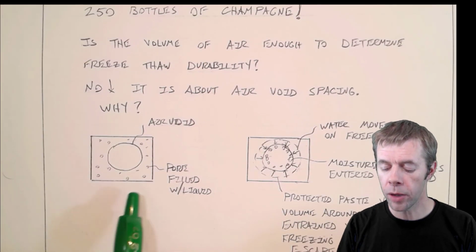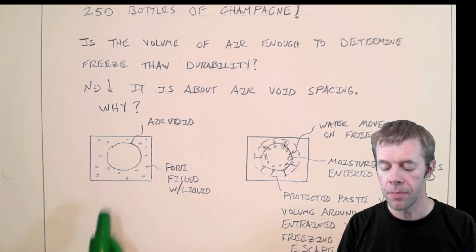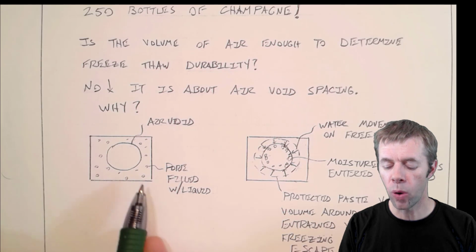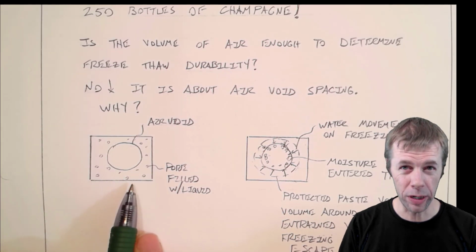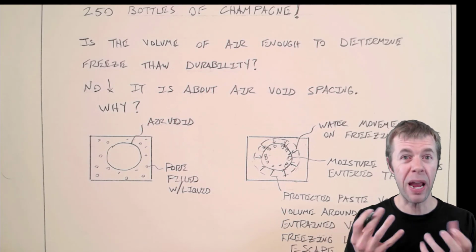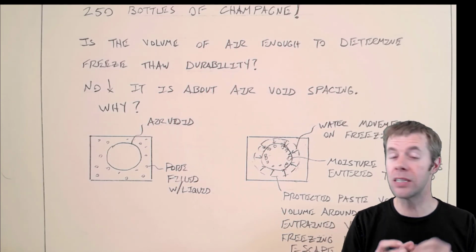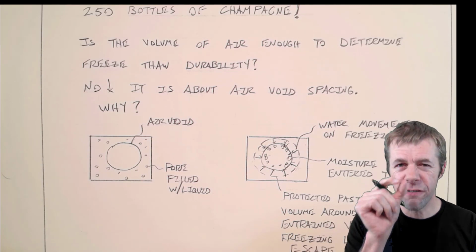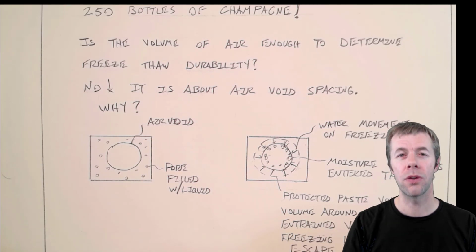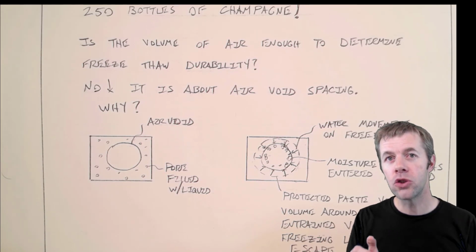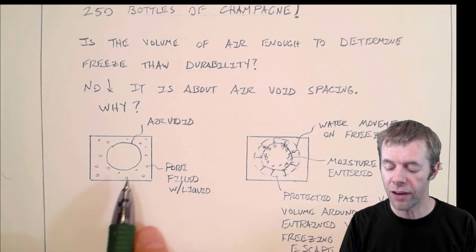Well, I'm showing a picture here where I have an air void, and around it is paste. And these are little bitty pores that are filled with liquid. And upon freezing, the water tries to expand. There's about a 9% volume change that tries to happen when water starts to freeze. And it freezes in these very, very small pores, okay? And it actually shoves water to the large bubbles. They actually travel to the large bubble.